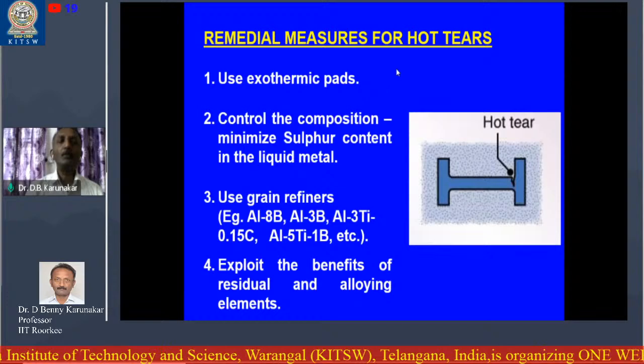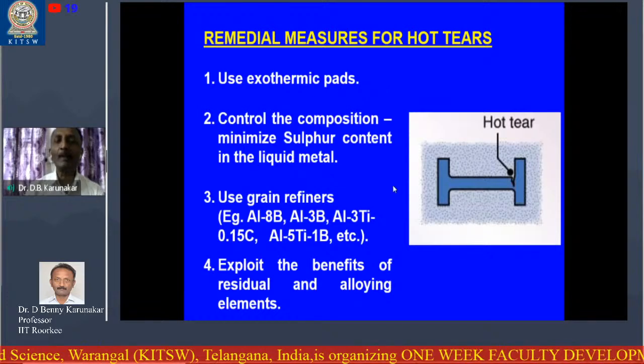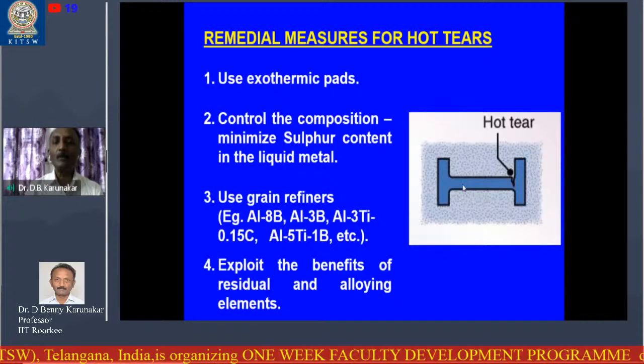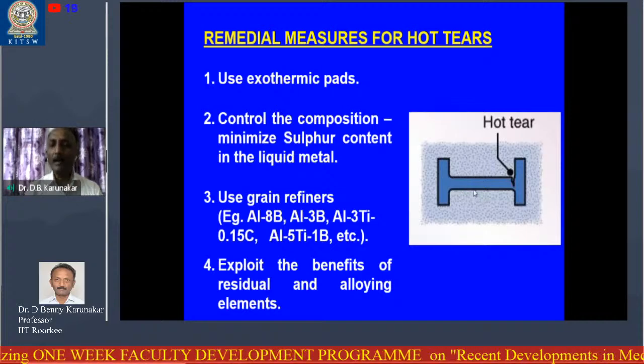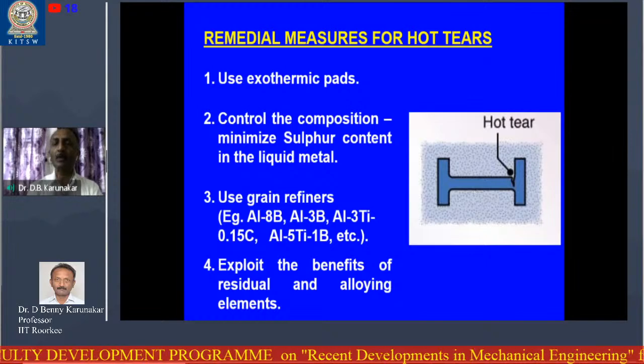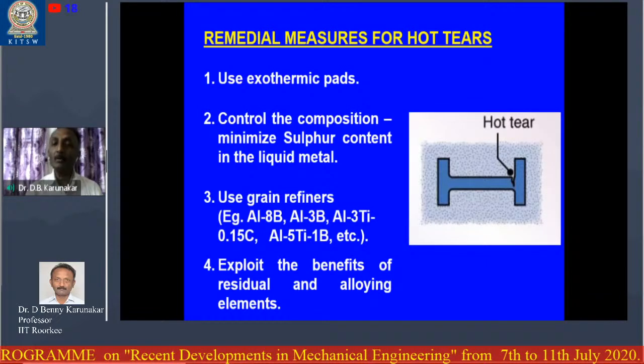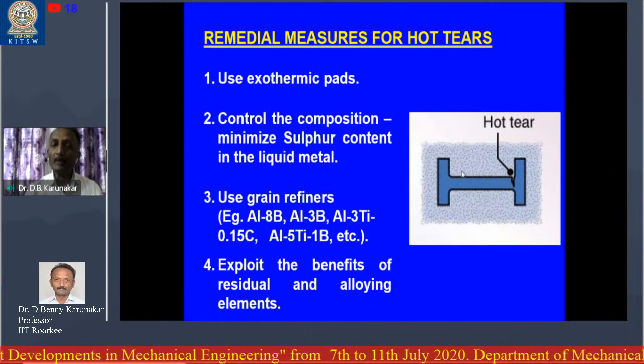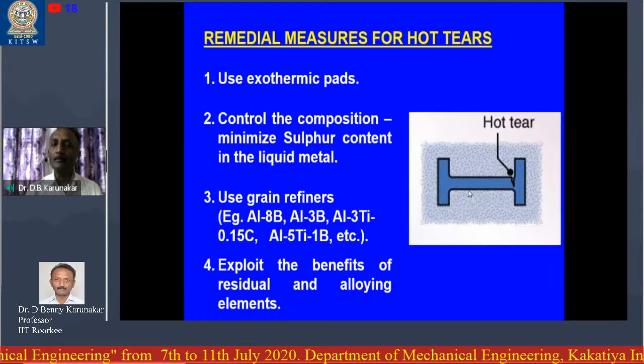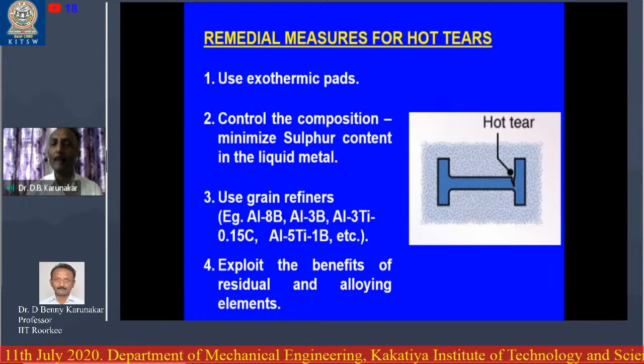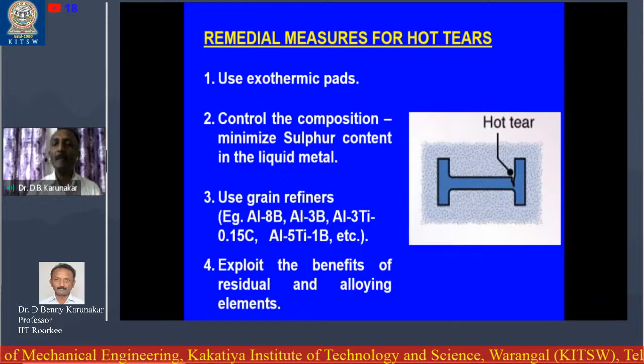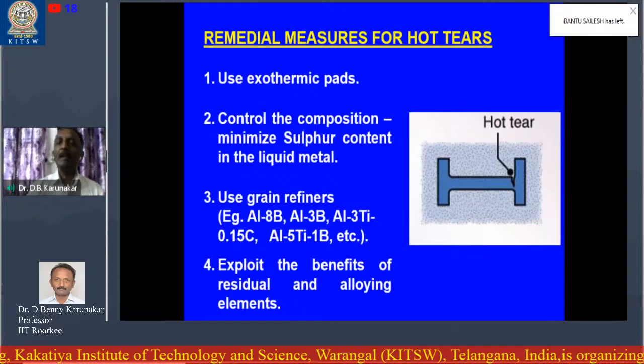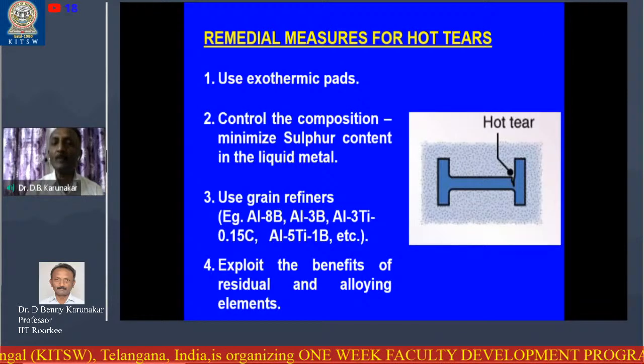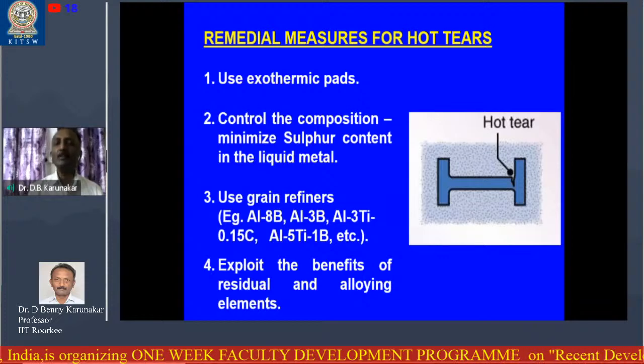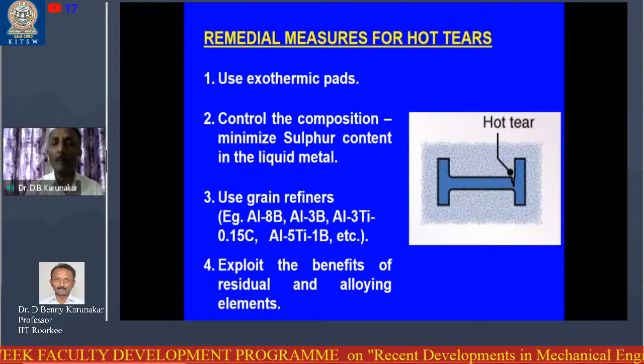So these are the remedial measures for hot tearing. Use exothermic pads. Suppose the inner section has already solidified and wants to undergo contraction, but the other portion is not. So you can put an exothermic pad around the inner section. Because of this pad, heat dissipation is slower, and it takes longer for solidification, so it may solidify in parallel with the other sections. The whole casting solidifies at the same time, not at different times in different regions, so this problem won't arise.